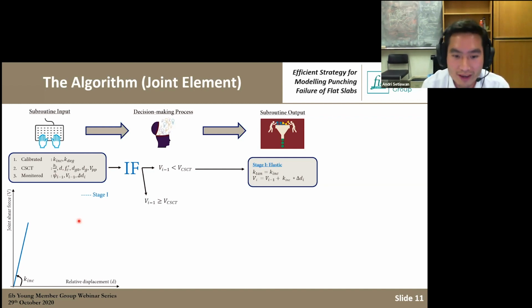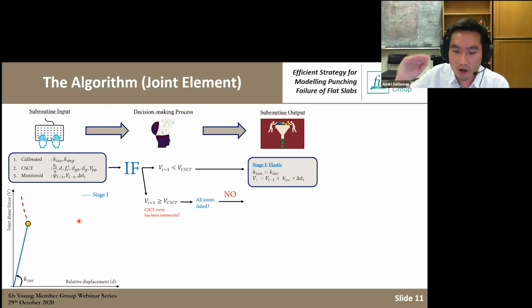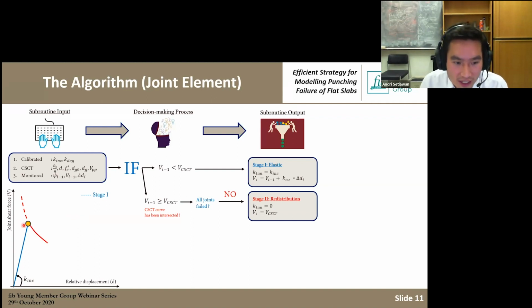Now, the second stage is that the shear force in the joint is already larger than the critical shear crack, so you have failure. But now we need to ask the joint element, did the failure happen on all joints or only at one joint? Why do we need this? Because we want to consider shear distribution. Shear distribution happens when one of the joints fails and some of the joints have not failed yet. So for example, if we find out that failure only occurs at one joint, we say that this is not a global failure, this is just a local failure. Let's go to the redistribution stage. At this stage, you can see in the figure, the resistance is no longer increasing, but it is decreasing following the shape of the critical shear crack theory curve.